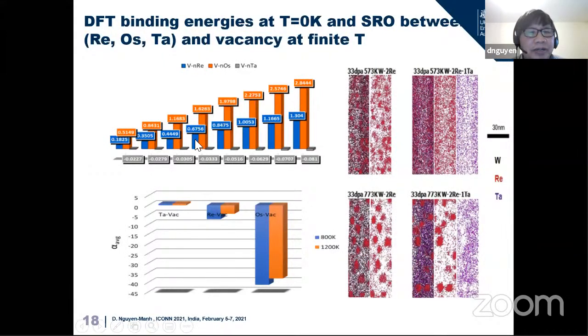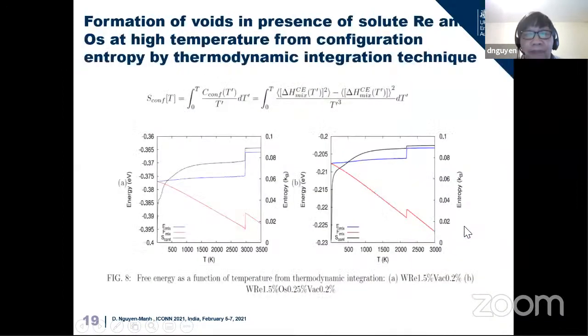So you can see that for tantalum, it's negative, meaning they're not binding with vacancy. Importantly, it is also shown in the atom probe tomography picture that tantalum is not essentially forming precipitation with rhenium, and it essentially behaves quite differently.